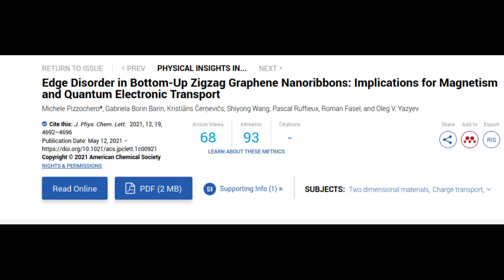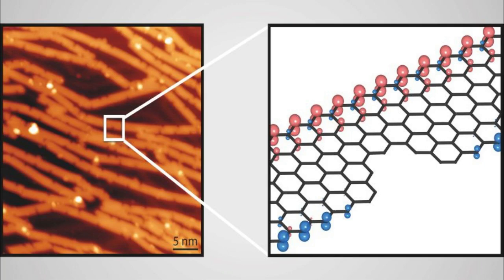In the paper, Edge Disorder in Bottom-up Zigzag Graphene Nanoribbons, Implications for Magnetism and Quantum Electronic Transport, recently published in the Journal of Physical Chemistry Letters, the same team of researchers combines scanning probe microscopy experiments and first principles calculations to examine structural disorder and its effect on magnetism and electronic transport in so-called bottom-up zigzag GNRs, ZGNRs. ZGNRs are unique because of their unconventional metal-free magnetic order that, according to predictions, is preserved up to room temperature. They possess magnetic moments that are coupled ferromagnetically along the edge and antiferromagnetically across it.